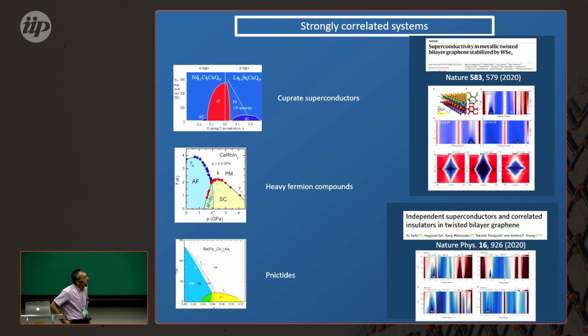First of all, as this is a diverse audience, let me mention that the key problem in this new class of moire materials is how similar or different they are from more conventional, strongly correlated systems. All of them share a complex phase diagram with both magnetism and superconductivity, but the main difference, in my opinion, is that in moire systems, superconductivity is much more prevalent. You find superconductivity more often, and moreover the so-called insulating phases are not terribly good insulators. The resistivity is always on the order of a few kilo-ohms, which is way below the typical resistivity of an insulator. The main reason they are called insulators is because the resistivity rises a little bit as the temperature is lowered.